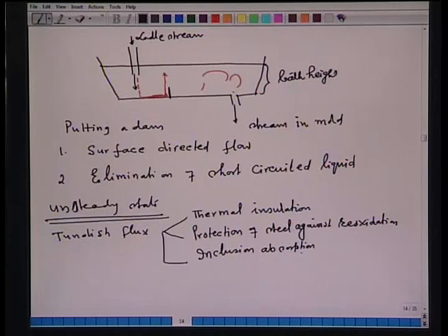So, constantly the molten steel in the Tundish is covered by a slag layer. Now, the slag layer has two functions: for inclusion to be absorbed, the slag should be liquid. For protection of steel against reoxidation and thermal insulation, if it is solid, it is better. So, the Tundish slag is selected such that it has both the roles during the continuous casting. So, this is about the development in the Tundish.